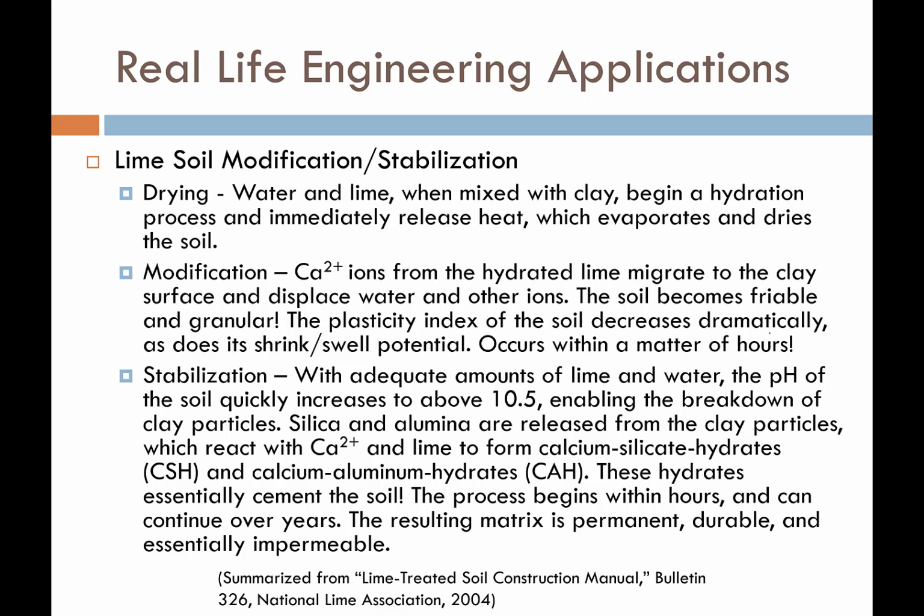It's pretty incredible. And then eventually, if you add enough lime and water, you reach stabilization. Okay, the pH of the soil will quickly increase above 10.5. So it becomes very, very basic. Okay, and then that enables the breakdown of the clay particles. Those sheets just break apart, and it becomes very, very brittle and very, very friable.